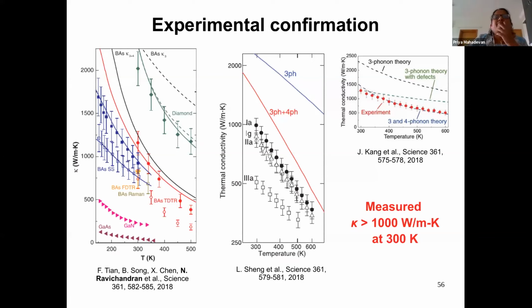So I just wanted to mention here that even though 4 phonon scattering is having such a large effect on the thermal conductivity of boron arsenide, the measured value in all 3 works is still exceeding 1000 watt per meter Kelvin. To give you some perspective, silicon's thermal conductivity is only about 150 watt per meter Kelvin at room temperature. So this is about a 6-fold increase in the thermal conductivity.